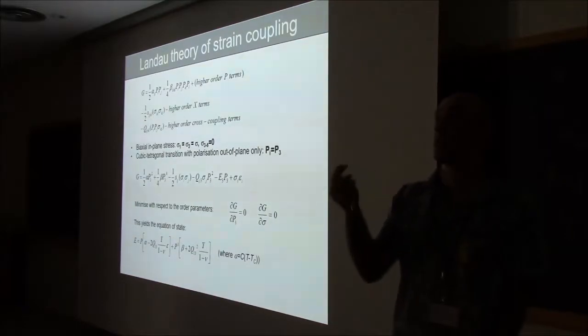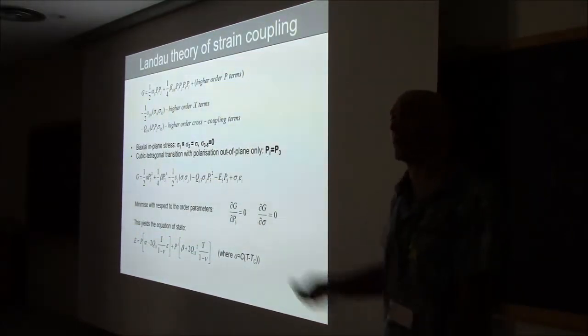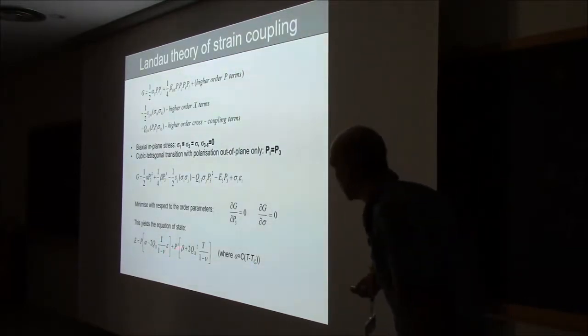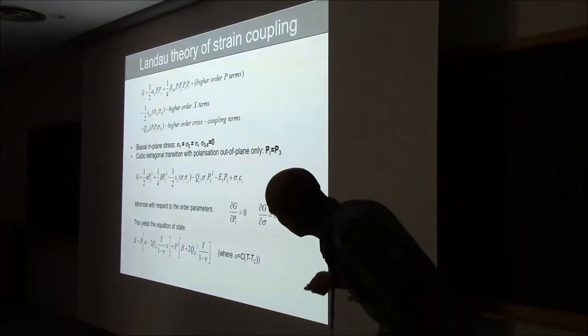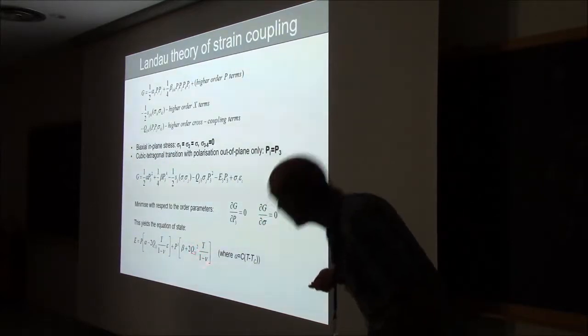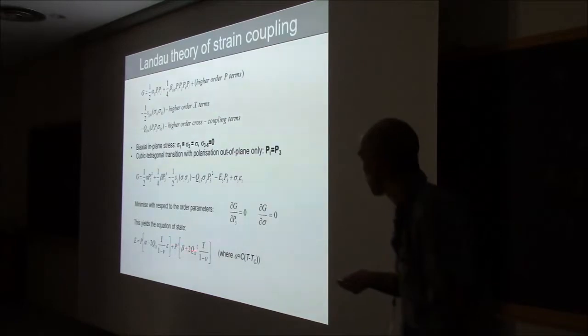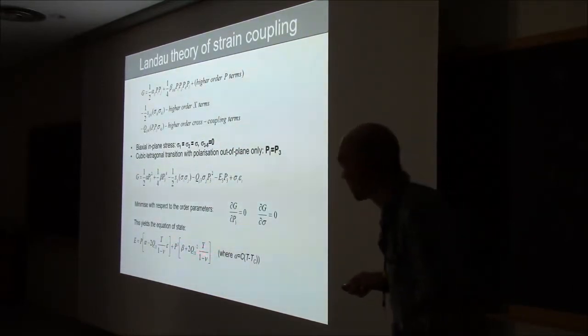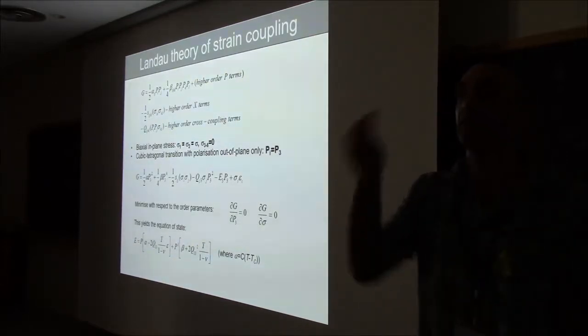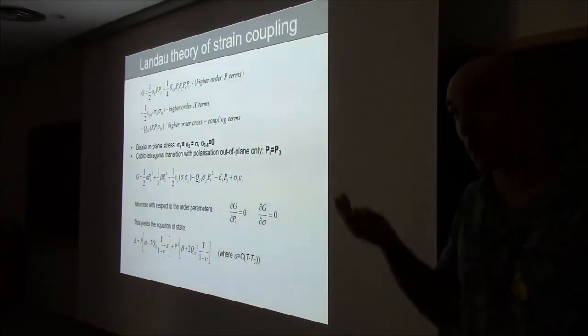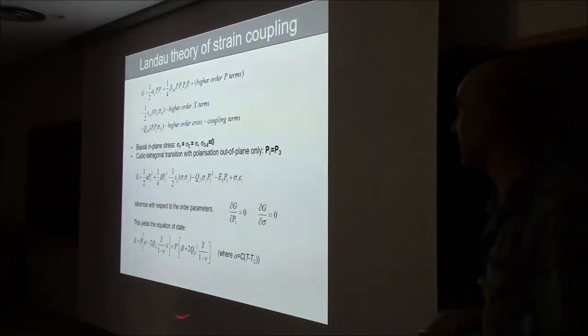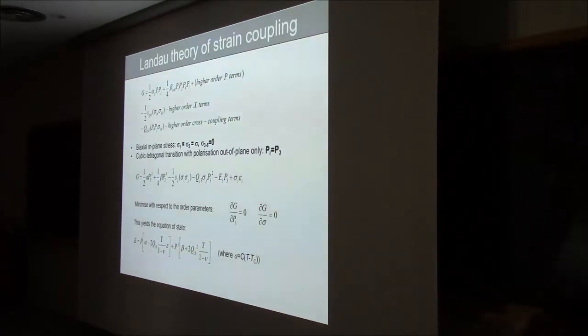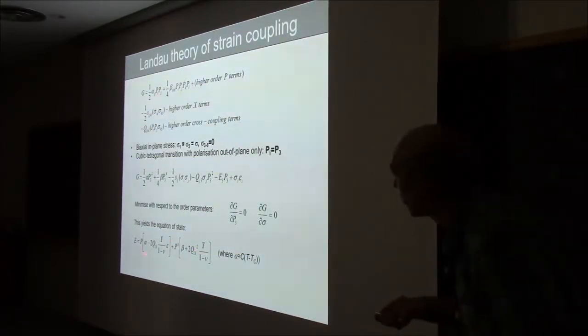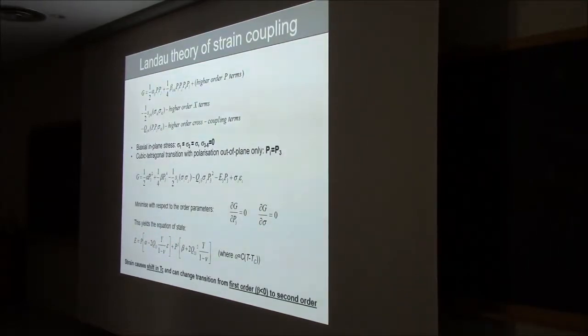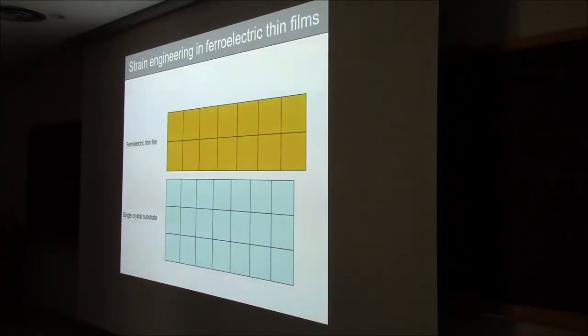And beta is the one that is telling you whether something is first order or second order. So you can start with something that is first order, where beta is negative, but as soon as you put the strain coupling, notice that this is the Young's modulus, which is positive, this is Poisson's ratio, this is positive, this is the electrostrictive coefficient, which may be positive or negative, but it's squared, so it's also positive. This is positive. Typically, this is not only positive, but bigger than beta. So even though most ferroelectric phase transitions are first order in bulk, when you make it in the form of thin films, the epitaxial clamping turns them into second order. Okay? So you can use strain to change the order of the phase transition, or to change the critical temperature. That has been done. Okay? You see? And this is how it works.